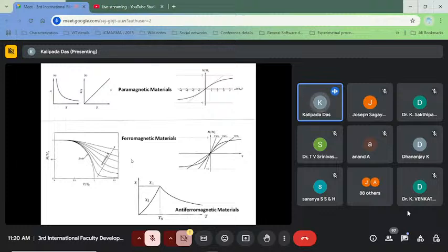However, in the case of a ferromagnetic sample, magnetic ordering is there, and below a particular temperature, that means the Curie temperature, the magnetic domains are oriented along a particular direction. If we apply any magnetic field, they will be directed towards the magnetic field direction, and above this Curie temperature, the paramagnetic ground state is found. In the case of an antiferromagnetic material, the magnetization initially increases with temperature, and above a particular temperature, that means the Néel temperature TN, it shows paramagnetic behavior.